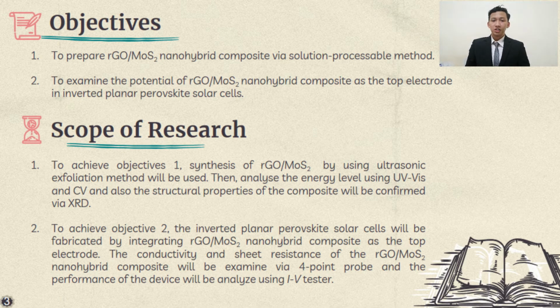The objectives of this research are, first, to fabricate RGO MoS2 nanohybrid composite via a solution processable method. Second, to examine the potential of RGO MoS2 nanohybrid composite as electrodes in inverted planar perovskite solar cells. For the scope of this research, we will use a solution processable method, which is ultrasonic exfoliation, to produce RGO MoS2 with 6 different weight ratios to achieve the first objective.